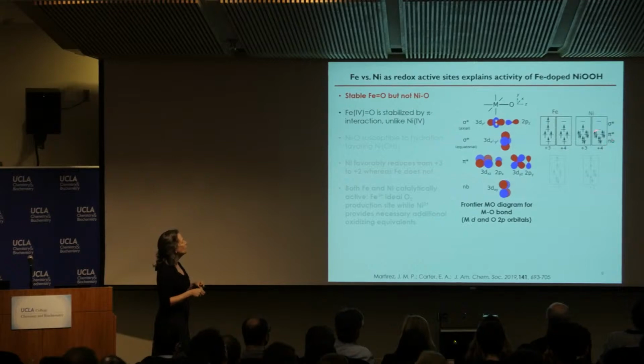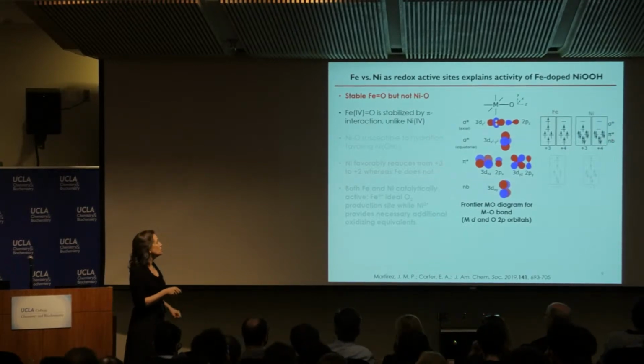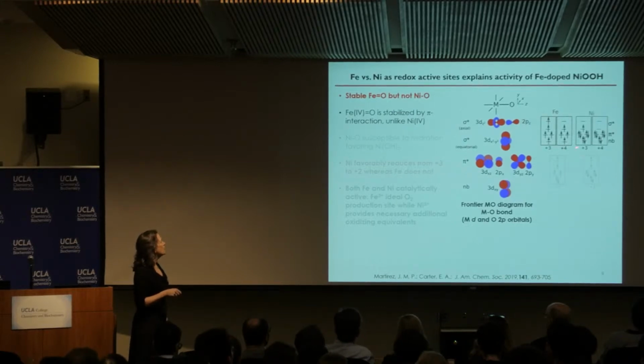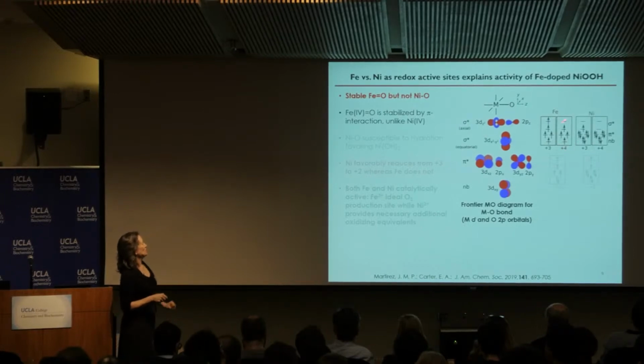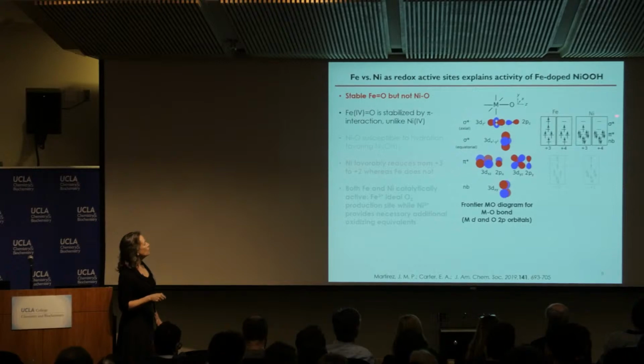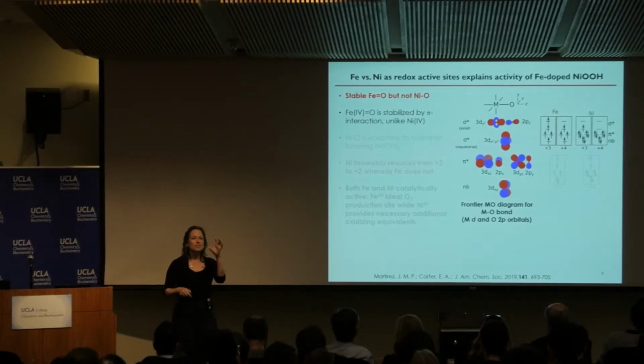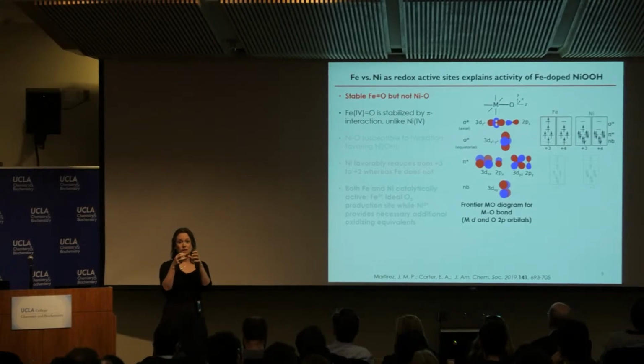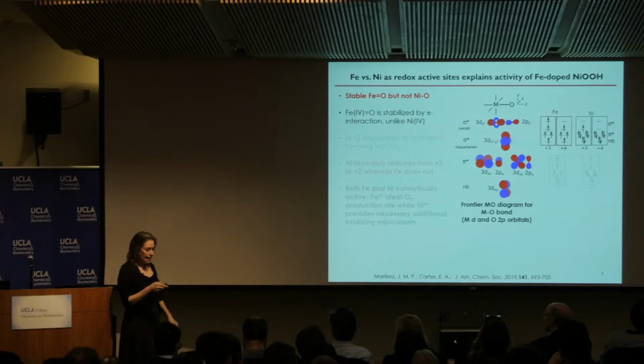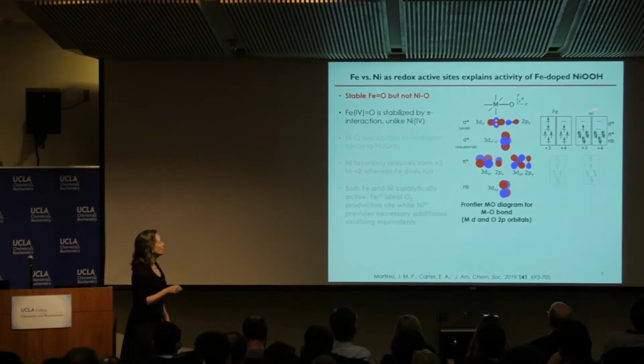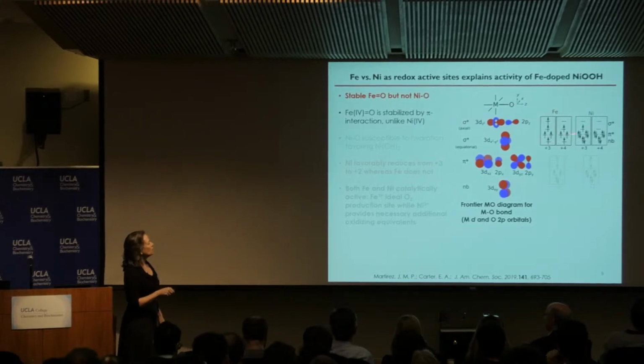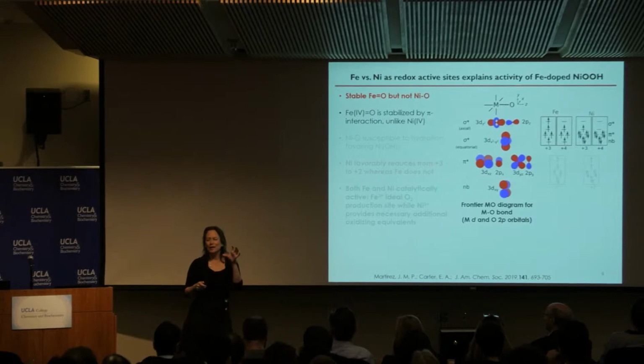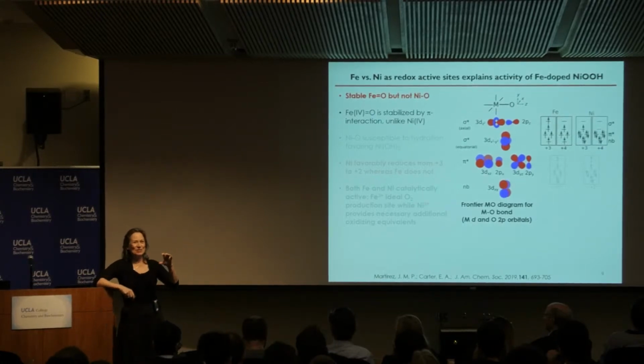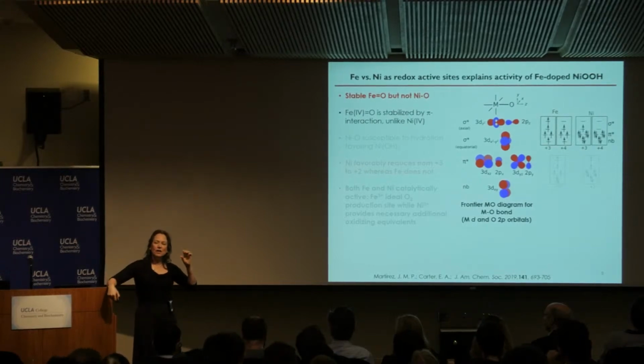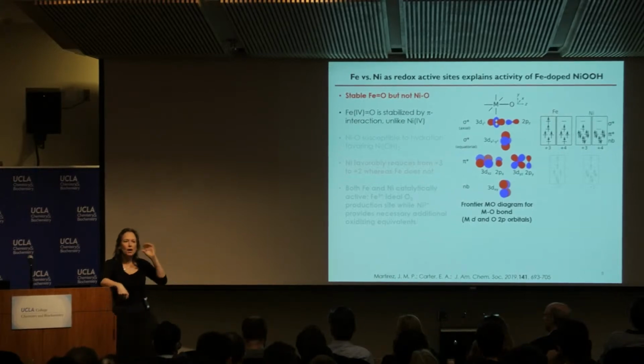And so it turns out in the case of nickel, you don't make high spin nickel. Okay, so actually it's a low spin nickel that is present in these materials. Anyway, why is that important? It's in fact incredibly important, because if you look at the iron 4 versus nickel 4, the difference is that in the case of nickel, the pi star levels are 100% occupied. And this is a picture where you think about O double minus as the oxo ligand. And so its pi's are occupied as well. And so what you have essentially is a very unstable nickel oxo situation, whereas here you have unpaired electrons in the pi star level. So it actually has a bond. This kind of picture goes back to work I did as a graduate student of bonding that looks like the same kind of bonding you have in the dioxygen molecule, where you have a pi resonance going on.